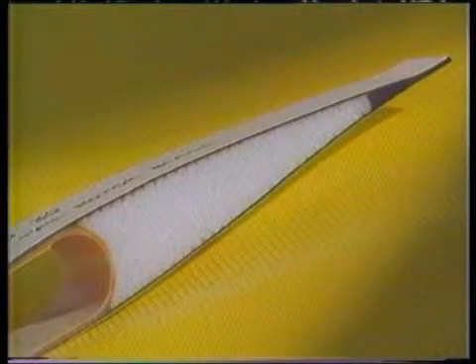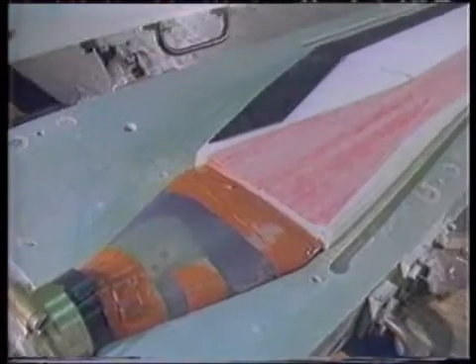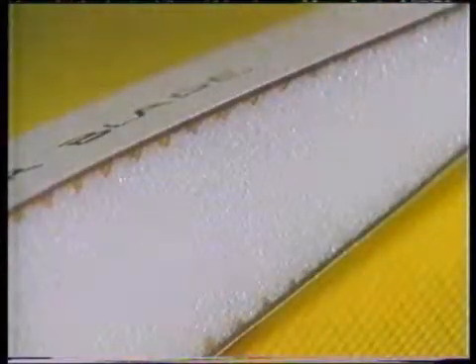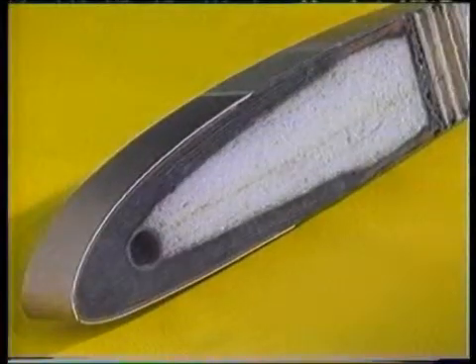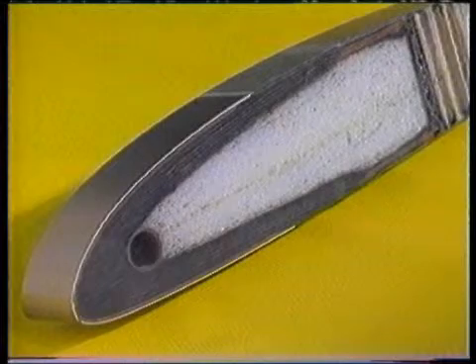The foam core has been accurately machined to oversize. The composite skin is consolidated by reacting to the compressive forces applied to the foam core. The skins are positioned in the mold halves, the core is located, then the aluminum tool is closed, pressing the prepreg layers against the oversized core. A heated press provides the force to precisely compress the blade skins and the machined foam core.